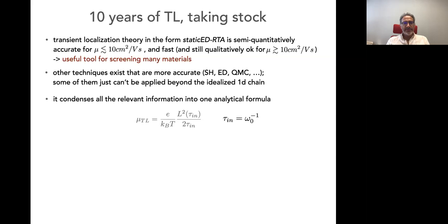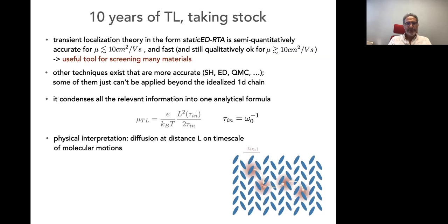Now, the other characteristic is that all the relevant information is condensed into one analytical formula. So why is this important? Well, because now if you want to improve your material, you know where to act. You can vary temperature, because if you want a material to work at room temperature, this is what you have. So you basically can change this localization length and this time scale. And first of all, this is nice because we had this sketch of how things would move, and then by seeing the movies, like the movie that was shown in the previous talk, it really looks like what we had imagined. That was a wild guess somehow, just by reading this formula, and it seems to work.